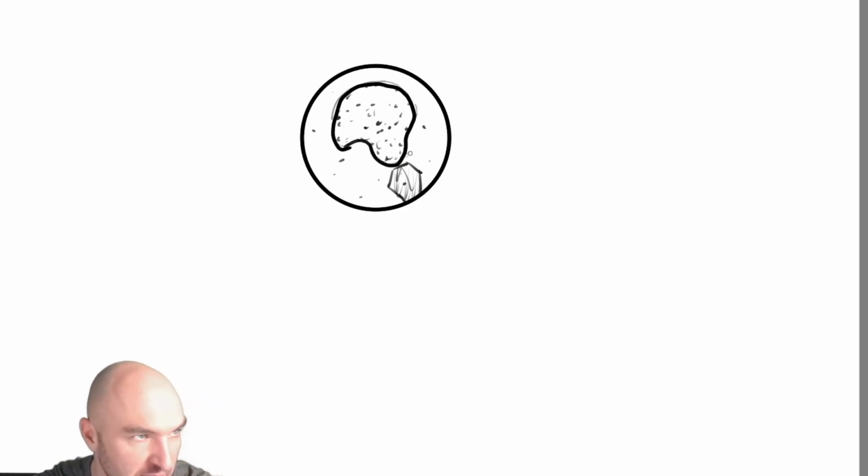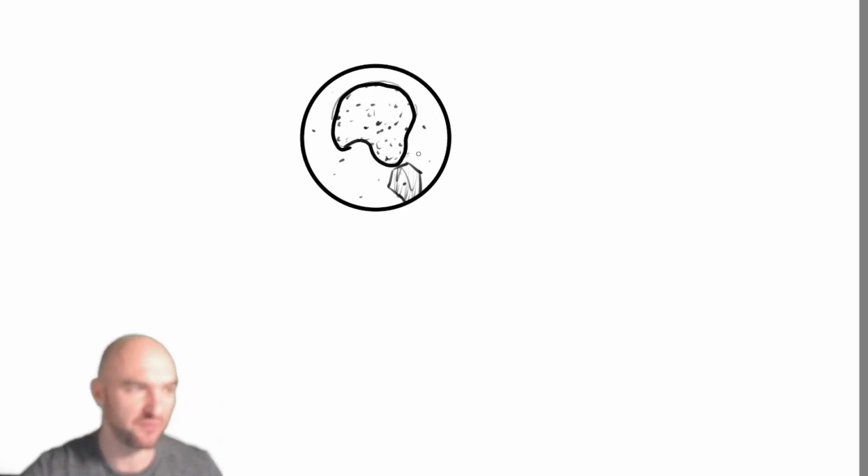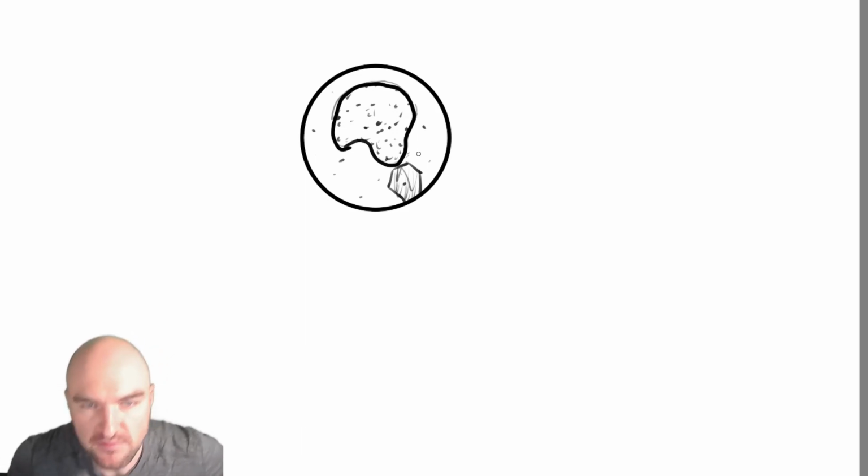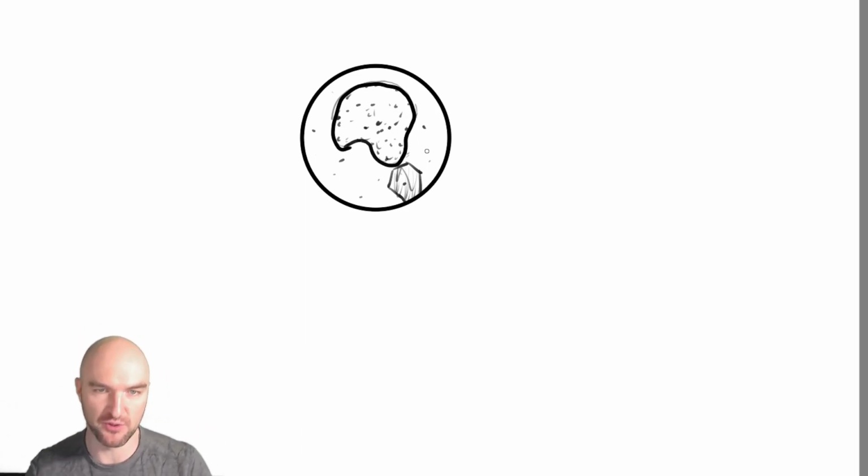It essentially says, okay, this area is closer to this hit than to any other hit, and because this area is very large, we're going to throw that hit out. Then we draw our alpha hull once we've thrown out all of those hits that have large areas around them where there are no other hits. That's called a Voronoi filter, and it gets rid of the noise.